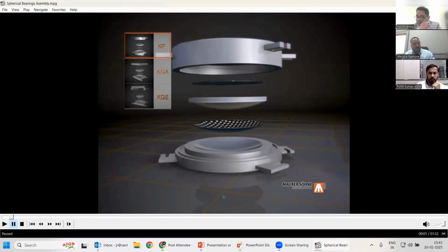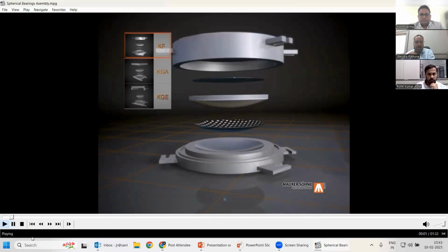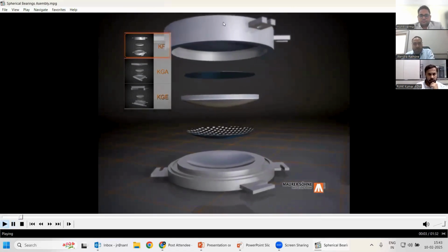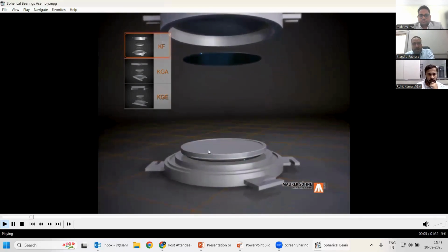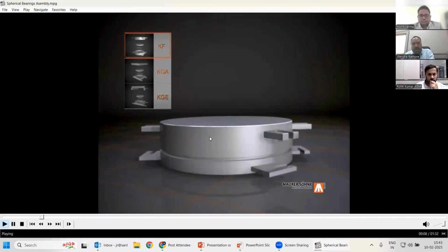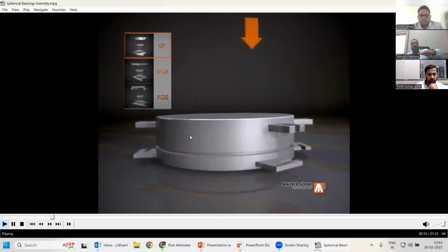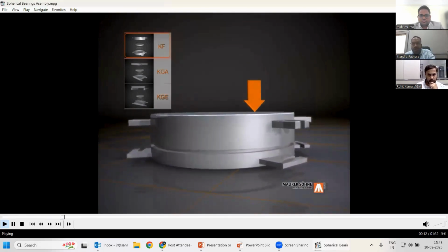Some manufacturers do it, but they have to be very careful in checking whether that shift in plan from the top component is within the capacity or purview of the superstructure, or it is going to adversely interact with the structure. In this three component design, which most of the manufacturers in India are by and large following, the top component is locked with the bottom and the rotation is done by this middle component. But the top component is then not dislocating from its position.